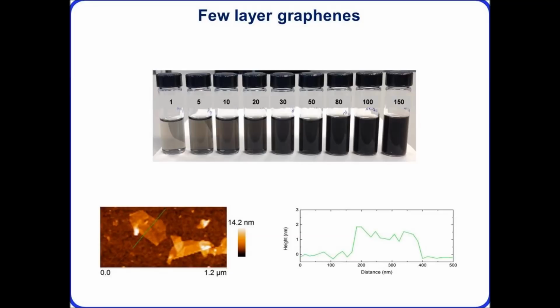One of the steps we've taken is to look at the process cycles of the microfluidic processor. We even went up to 150 cycles, and then we performed this centrifugation step. That's an essential step in the process, and now we are looking to find alternative ways of doing this separation, because it doesn't lend itself to being a highly industrial, scalable process. But with AFM we can see very thin sheets down to 1 to 2 nanometers thickness. We've done a lot of optimization of the process parameters and looked at different centrifugation parameters, as well as the microfluidic process pressures, and looked at the yields as a function of the starting graphite loading. Essentially, our yield for the process is limited to around 4 weight%. But that doesn't mean we're throwing away the other 96%. We are using the 96% for these other screen printing inks.